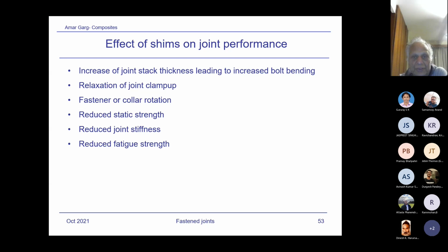Effect of shims on joint performance: increase of joint stack thickness leading to increased bolt bending, relaxation of joint clamp up, fastener collar rotation, reduced static strength, reduced joint stiffness, and reduced fatigue strength. As I said, shims are necessary evil sometimes. They don't help, they only degrade the joint.